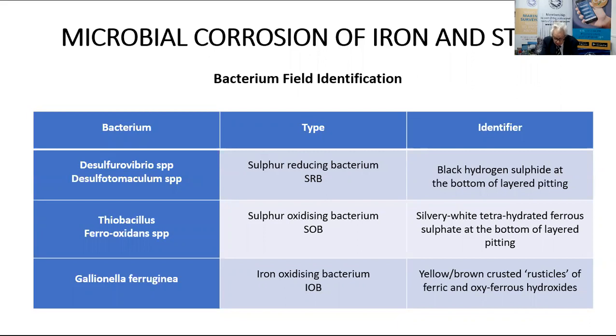Electrochemical methods of identification using a sulfur test can be used under controlled conditions, but it's difficult, takes a long time and is rather unselective. The common practice of non-blacking the underside of bottom plates of narrowboats in the canals, for example, can only encourage this form of corrosion, and indeed I have often found it in such places.